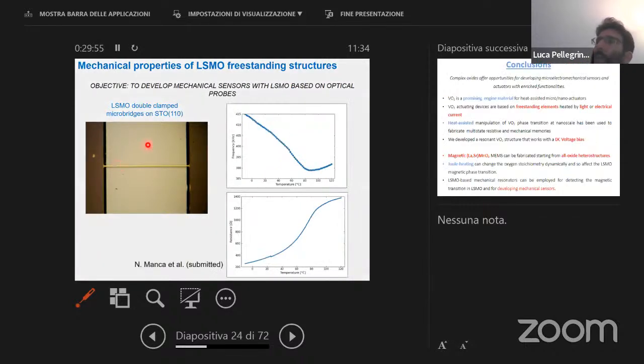And even in this case, we can detect the change of resistance associated with the magnetic phase transition of this structure as a function of temperature. At the same time, we can observe a change of resonance frequency. This is due to the change of the Young modulus, because here you have a magnetic transition. So you change the Young modulus and you change the tensile stress of this structure. So tensile stress is linked to the change of the resonance frequency of these mechanical structures.